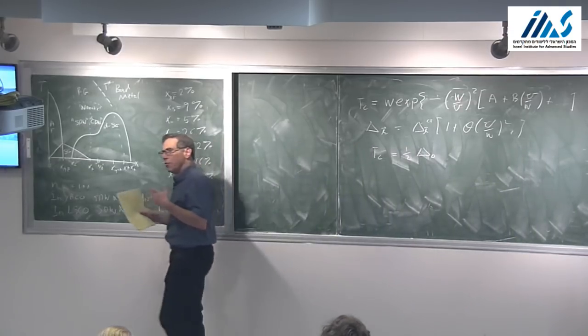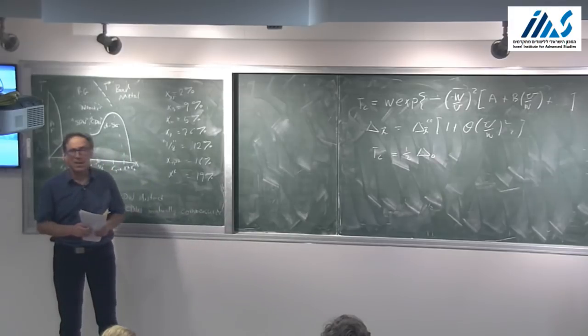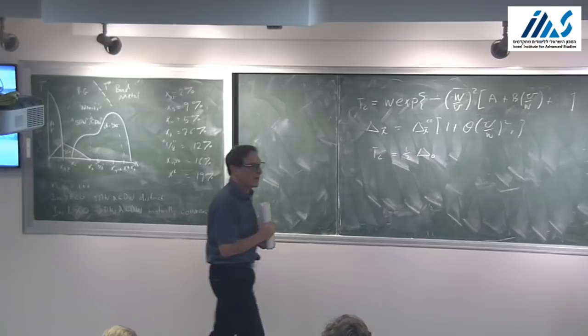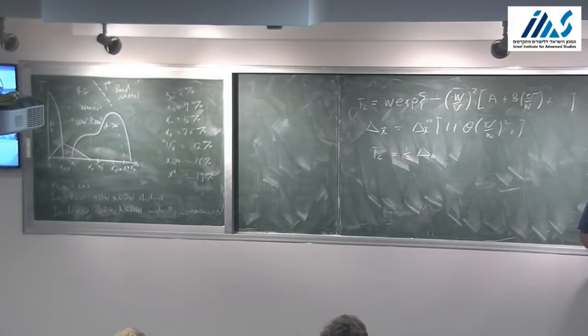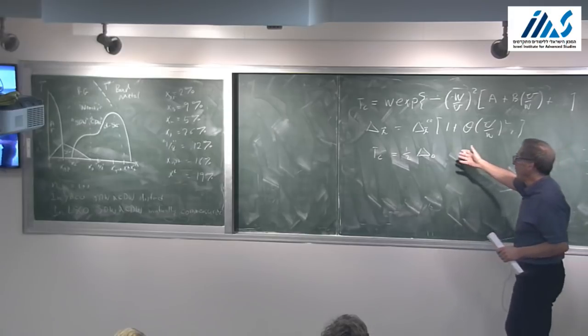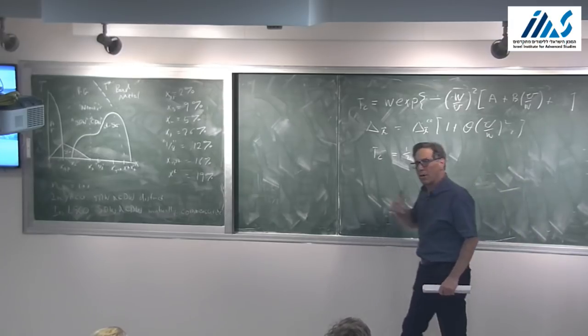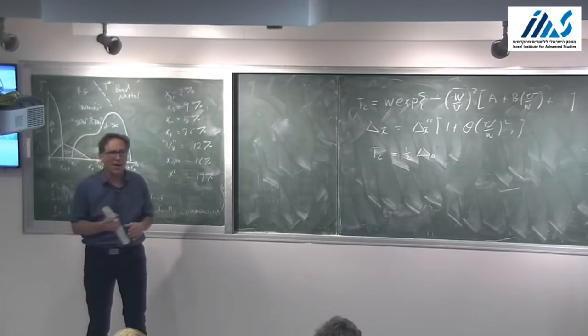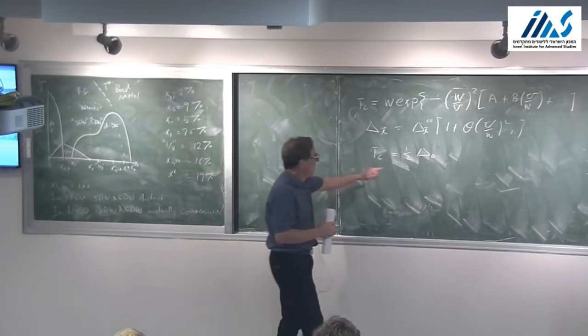That tells you, suppose you have access to zero temperature experimental data in the superconducting state, and somebody asks you, please predict TC. So in most conventional superconductors, you can do that easily. You just measure the gap, and then you know that the sorts of fluctuations that destroy superconductivity are depairing fluctuations. So the gap scale is what determines TC.